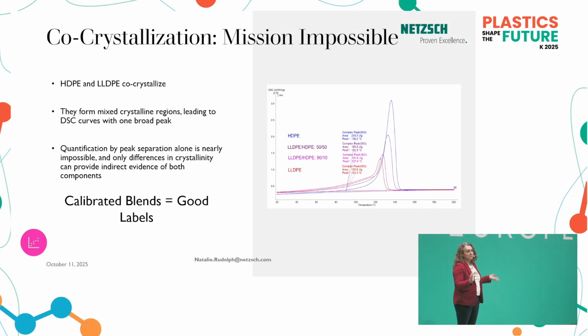And now Mission Impossible is really when materials co-crystallize, and that's the case when LLDPE and HDPE are put together in the waste stream. I show here a curve for the pure HDPE, in red the pure LLDPE, and in between. But you only see 4 different curves and no different peaks inside of a curve. That's because it co-crystallizes and it doesn't create 2 peaks that we can separate. So it's very important that we use calibrated blends and that we label them properly. And that's a hard learning.